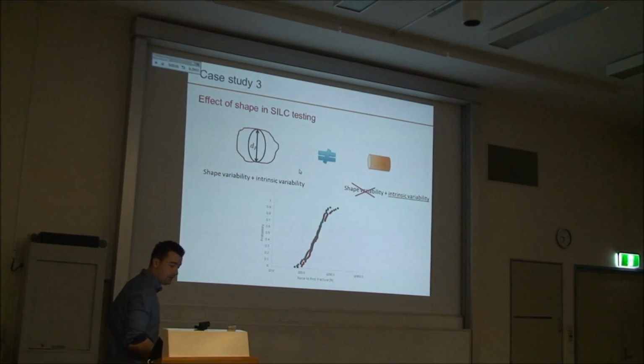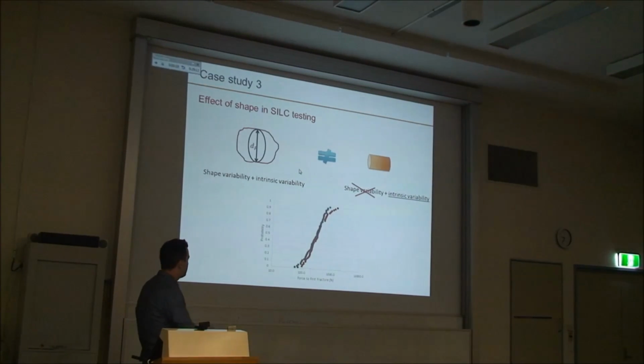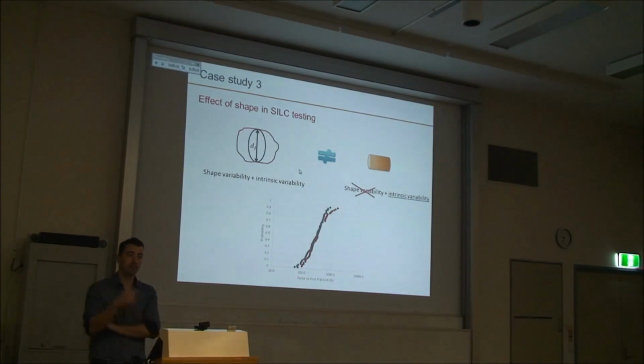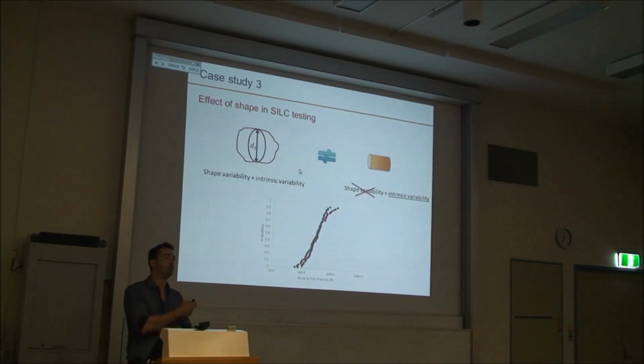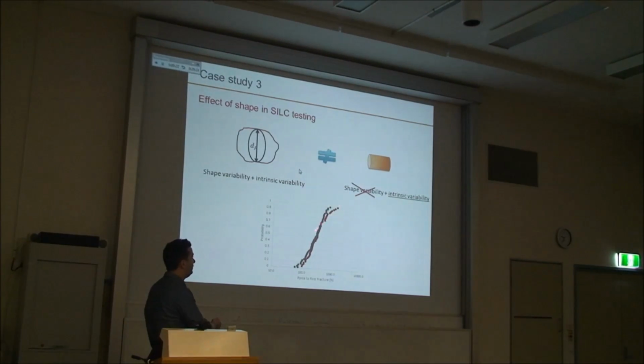So, the effect of shape. This is the third case study we've conducted here. The reason is that when you test two different samples, what sometimes happens is that you have the fracture force distribution, and the two distributions are actually very close to each other. So there are statistical methods to try to assess if they are different. You look at the spread, you look at the average, you look at different properties, and sometimes it's just impossible to differentiate two distributions.